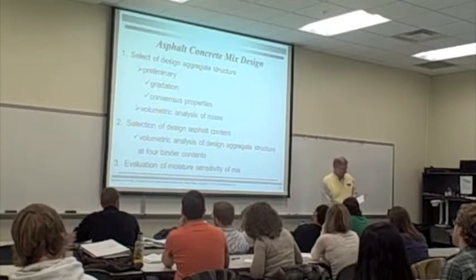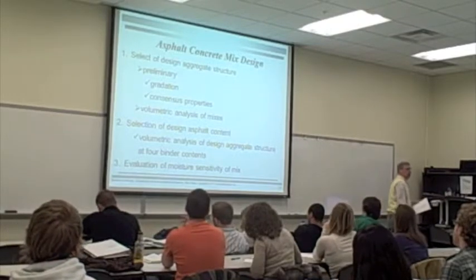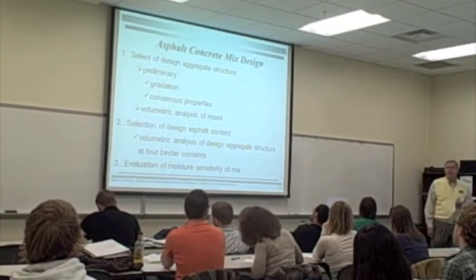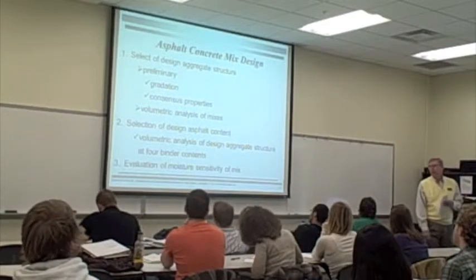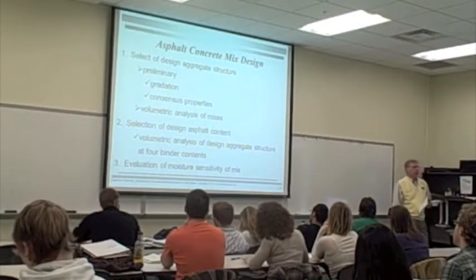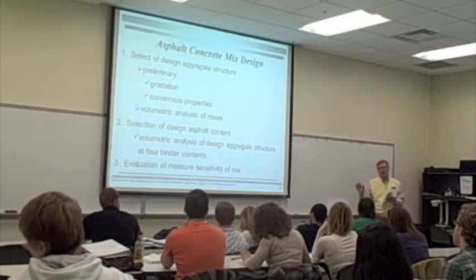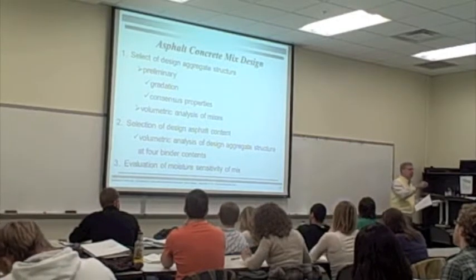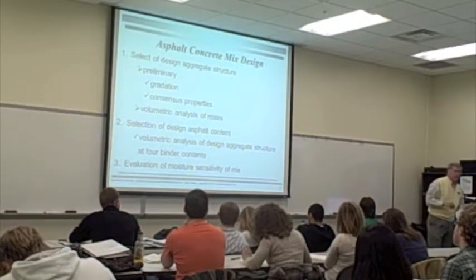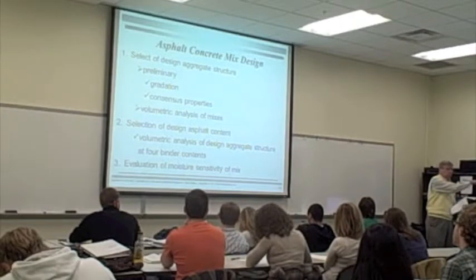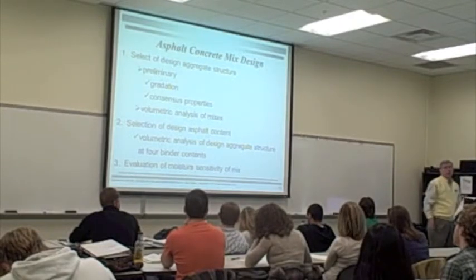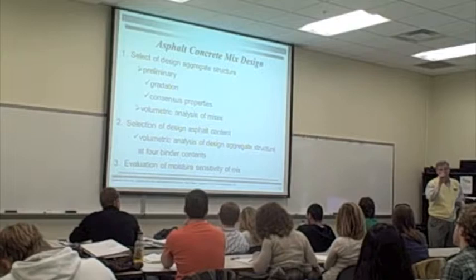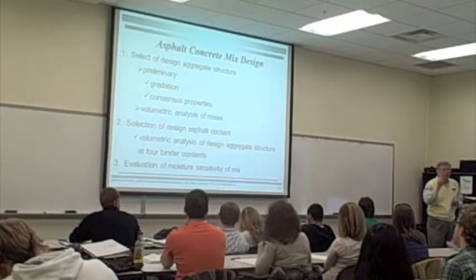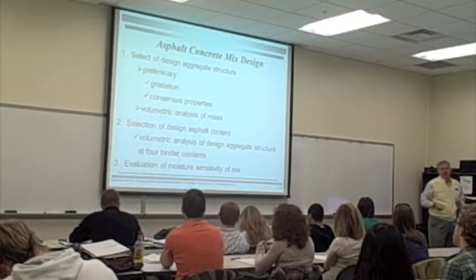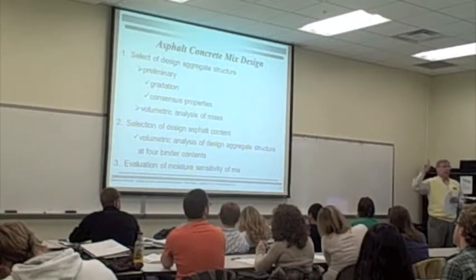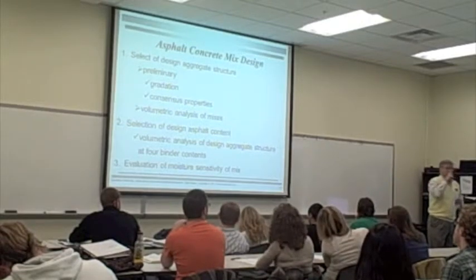The binder we select based on temperature. So for West Virginia we selected a 64-22. And if we have heavy traffic, we bump that one upper temperature grade, 70-22. If we have slow traffic, we bump one grade. So if we're doing city streets, we shouldn't use the 64, we should use the 70. Yeah, and the word should was appropriately selected, okay? And then if we have slow and heavy, then we want to bump 2 grades.